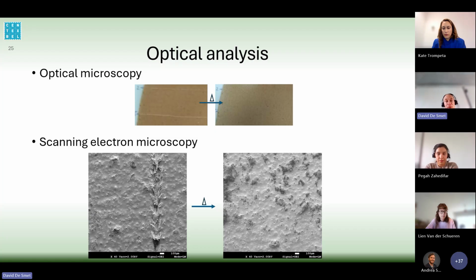What we can also do is look in more detail into the scratch by using scanning electron microscopy. And here you can also see at the left the damage made by the scratch into the coating. But just heating it at 80 degrees, you can see that the coating again will restore itself.